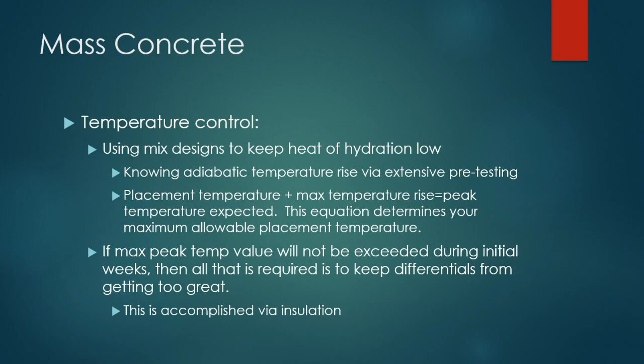Typically, you're going to want to place concrete at much lower temperatures than that. And as long as you know that the maximum peak temperature value will not be exceeded during the initial weeks as it's curing, then all you really need to do is keep the differentials from getting too high, because that's another factor for mass concrete: the maximum differentials, which is the difference between the core, the center of that mass, and the outside edge of that mass. And the way you do that is by using insulation.